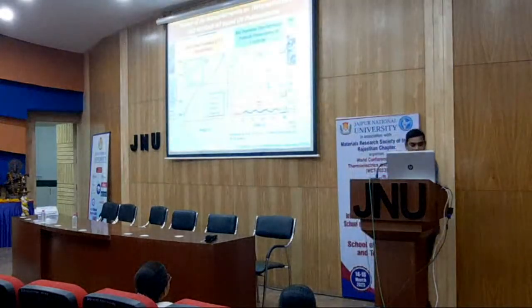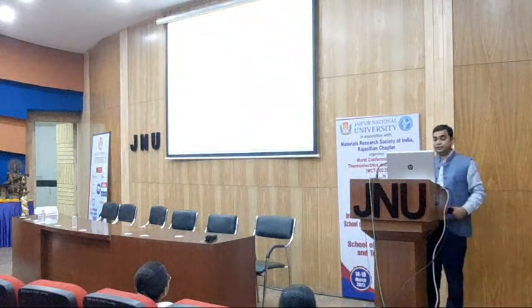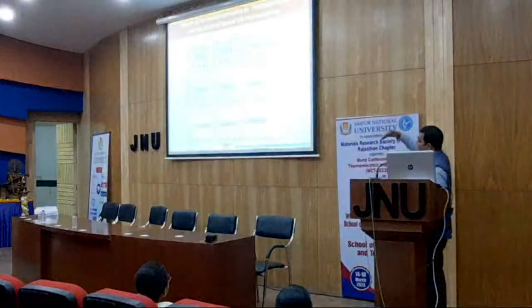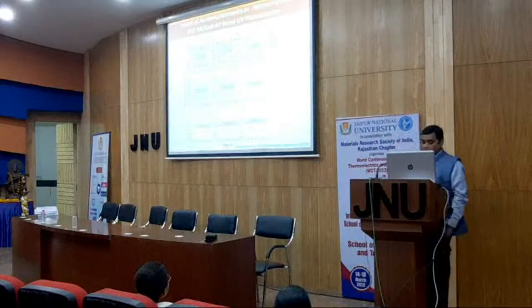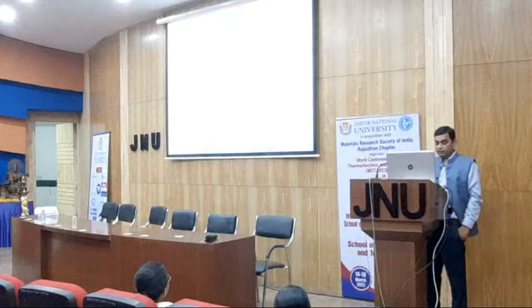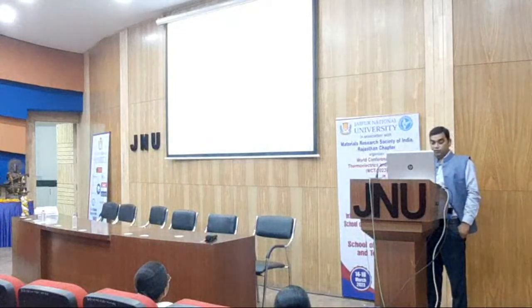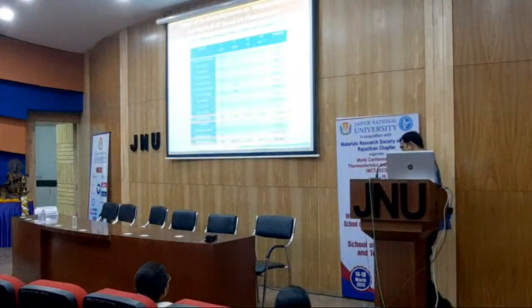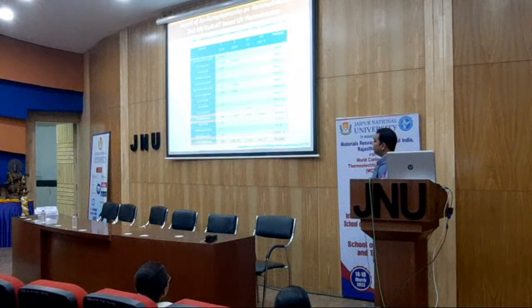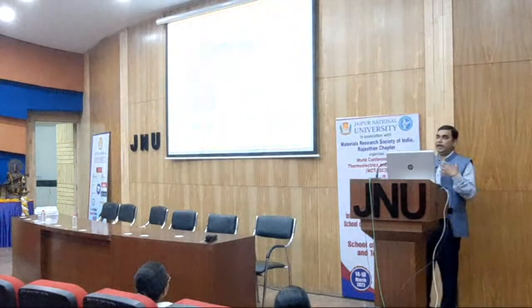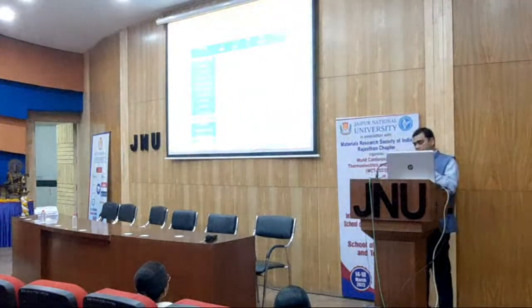So we are able to enhance the photocurrent maybe 10 times. You can see here, this is 2 milliampere to 27 milliampere after going to different stages. But when we are talking about the response time, I'll skip all those parameters because time is limited. And responsivity, we are able to achieve 7,000 ampere per watt, which is the highest we have reported. So response time, which we could get in microsecond, is going towards millisecond with a number of heterostructures. So this is a disadvantage of adding something on top without epitaxial nature.